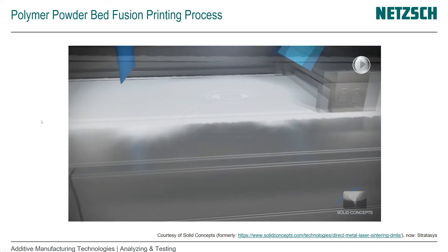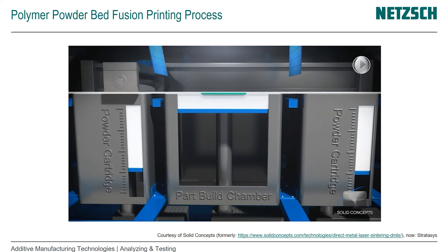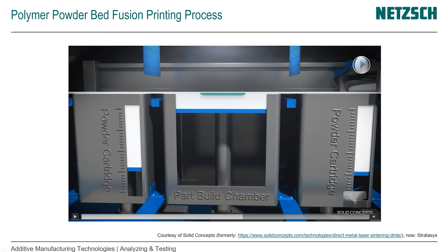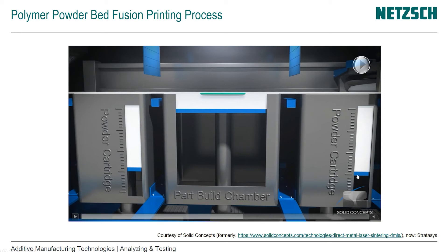We see the preprocessing — slicing and creating STL files of individual layers. The laser traces in blue, then we see powder being coated from left to right; powder supplies are on both sides. It gets shiny as it melts, new powder is applied, and the laser traces the next layer. Viewing from the front: the part build chamber is in the middle with powder cartridges on the left and right. The active cartridge moves the powder supply up, the roller sweeps over and deposits powder on the build chamber, then the opposite cartridge supplies powder for the next layer — so the roller doesn't have to move back between passes.